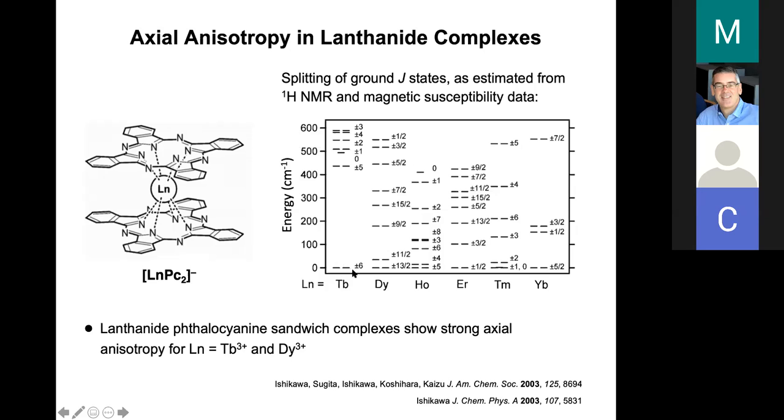And so this splitting is dictated by the ligands surrounding the lanthanide ions and the specific positioning and electron donating properties at all of these sites on the square antiprism. And if you want to build a good magnet with a large magnetic anisotropy, it's all about achieving a very large separation between these large moment M sub J states and smaller moment M sub J states.